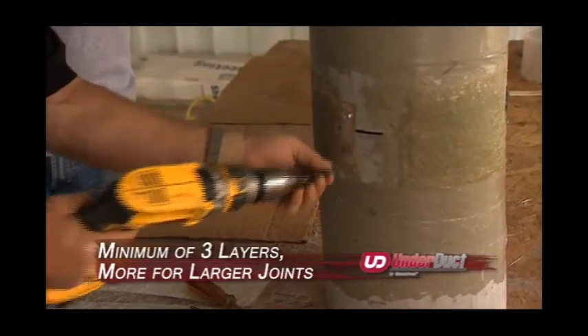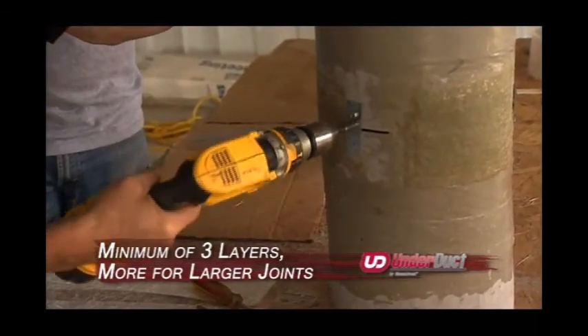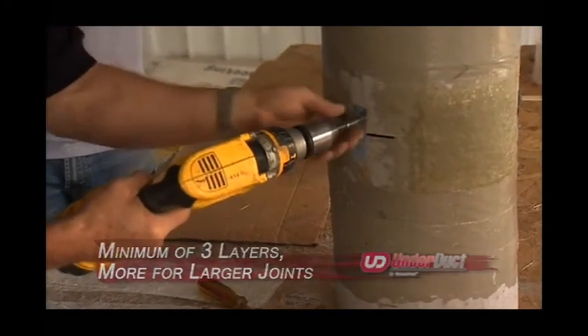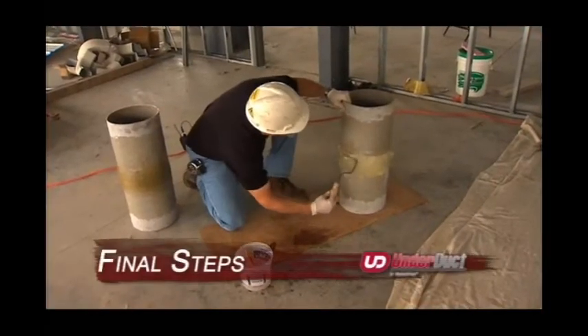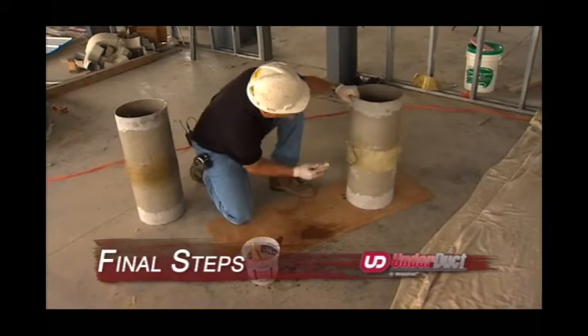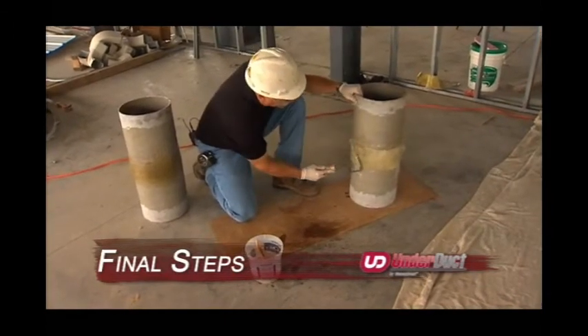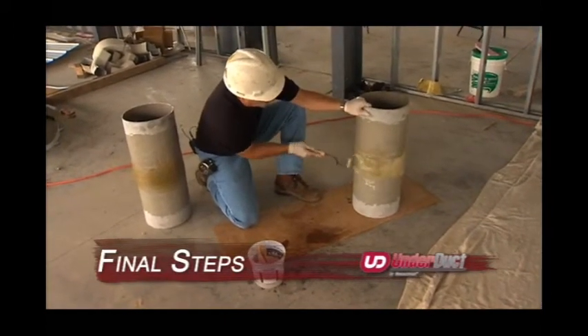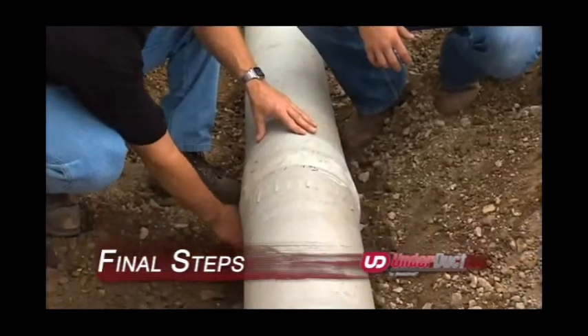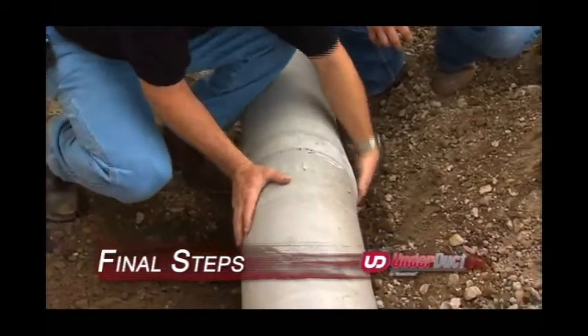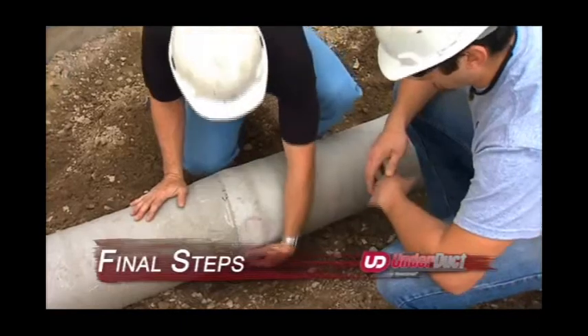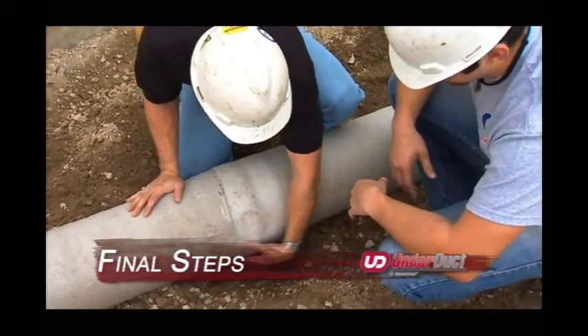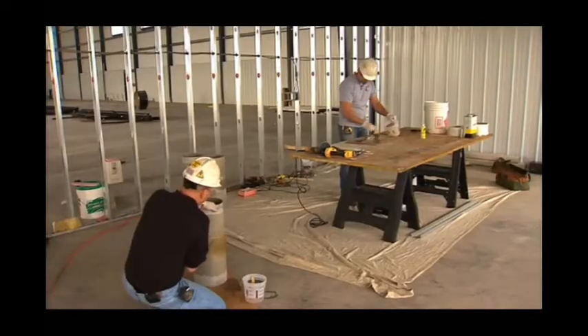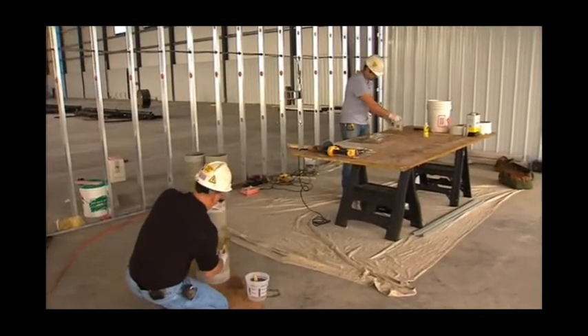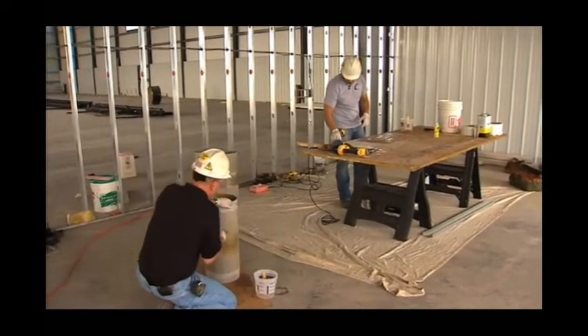After the hot patches have cured, remove the metal clips and finish the joint lamination. Thoroughly inspect all joints after they have been completed, grinding back and patching any air pockets or delaminations. For all above ground applications requiring a gel coat finish, be sure to grind any rough or sharp spots before applying the gel coat. Remember, proper field setup can save hours of installation time.